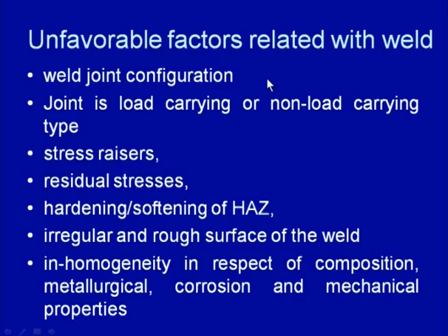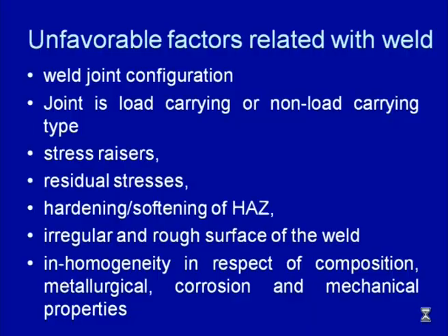So, the effect of the weld joint on the performance of the assembly will be different depending upon whether the joint is the load carrying kind or the non load carrying type. Then stress risers: weld joints frequently have stress risers in the form of ripples present on the weld surface in as welded condition, the presence of a crater at the end of the weld zone or the weld toe, sometimes cracks in the heat affected zone, and discontinuities in the form of porosity and inclusions are commonly present, and these frequently act as stress risers.